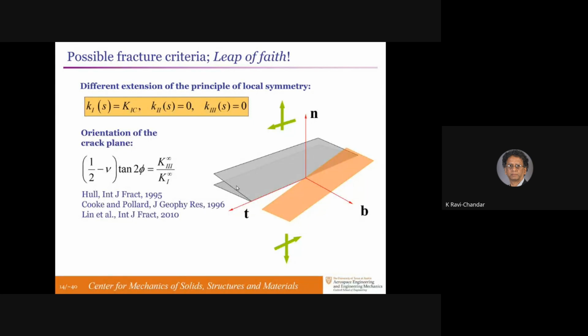So basically what it's saying is if I move to the left of this point, the crack should go up. If I move to the right of that point, the crack should go down, if you have a perspective from the B vector. But if I now move a little bit to the right or left, I can't enforce the same thing unless the crack fragments itself, which means it can fragment further. And there's no clear criterion on what sets the spacing for this fragmentation to occur. There's a lot of suggestions in the literature that this should be the criterion, and here are some references.